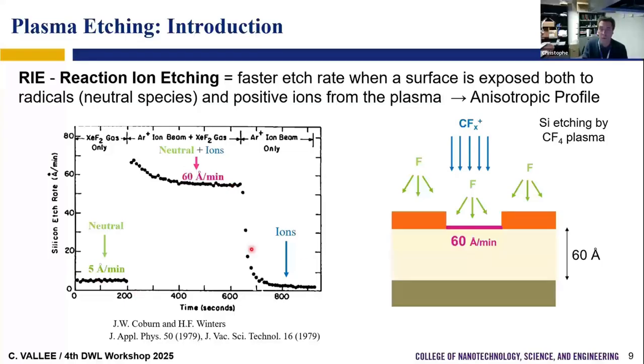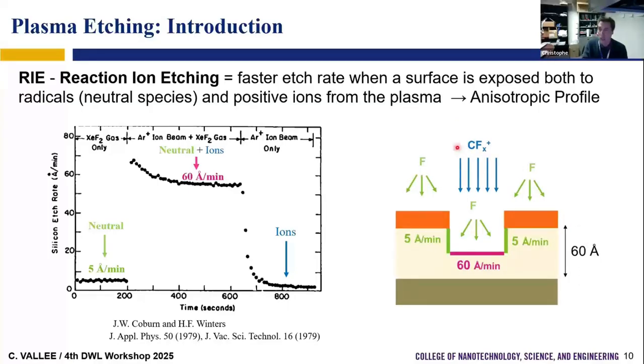And when you have only fluorine species, you etch at 5 angstrom per minute. And you want to etch 60 angstrom of material. So as you start to propagate the etching in this direction, it goes at the rate of 60 angstrom per minute because you have both.